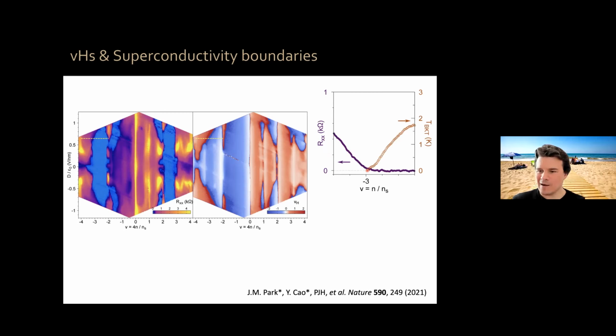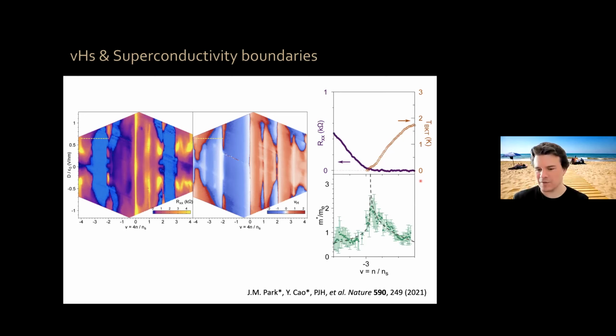Now, I can do measurements of the effective mass of the charge carriers in the system. By measuring the temperature dependence of quantum oscillations in the system, you can extract the effective mass, and I can measure that effective mass as a function of filling factor. The effective mass in a solid state system is proportional to the density of states. So when I measure the effective mass as a function of filling factor, the exact same trace.